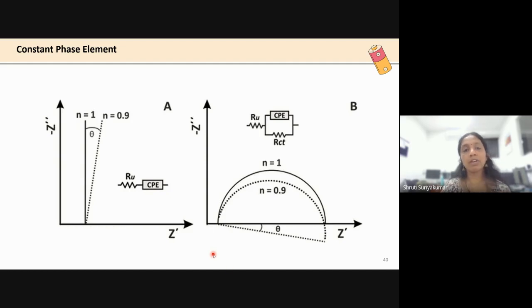And what happens with the constant phase element is that if you're running a capacitor, you're not going to get an Ru, and when you're running an instrument for a supercapacitor application, you're not going to get a straight line, you will be getting a slightly slanted line. That is because it is not going to fit with a capacitor but a constant phase element, and you attribute it to the roughness, the porosity, the thickness, all those parameters. So in series, your capacitive behavior is not going to be there, you're going to have a deviation.